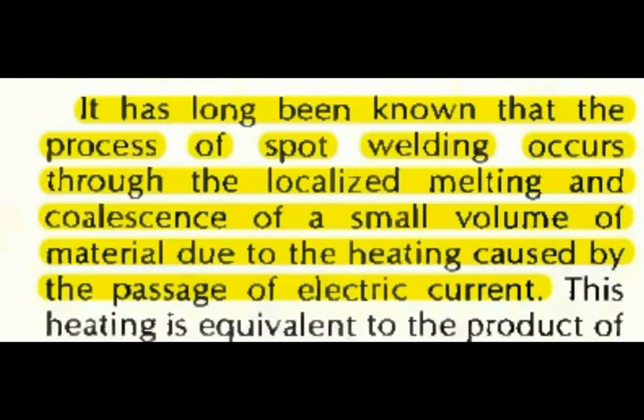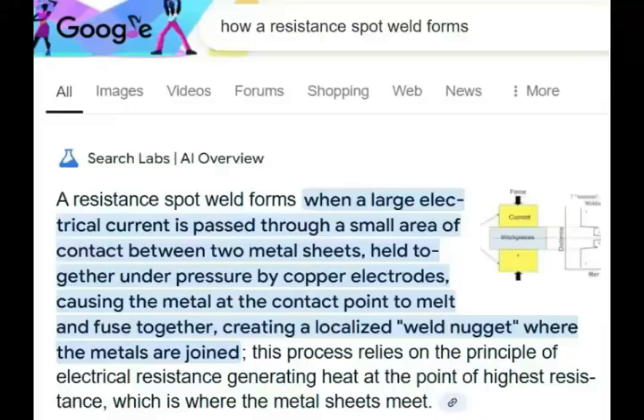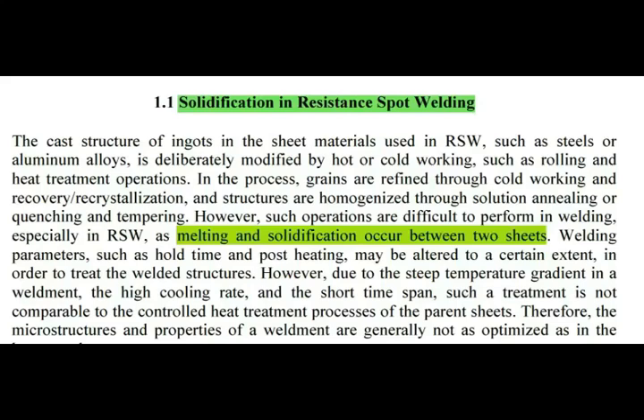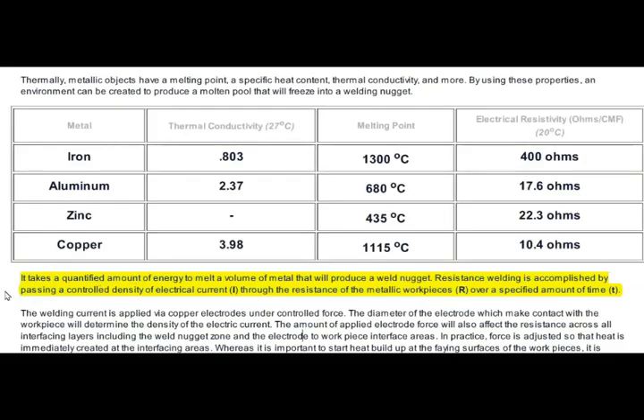It has long been known that the process of spot welding occurs through the localized melting and coalescence of a small volume of material due to the heating caused by the passage of electric current. The problem with their theory is they offered no experimental proof that you must melt in order to produce a weld. Melts the metal and fuses the two pieces together. Melting and solidification occur between two sheets. It takes a quantified amount of energy to melt a volume of metal that will produce a weld nugget.